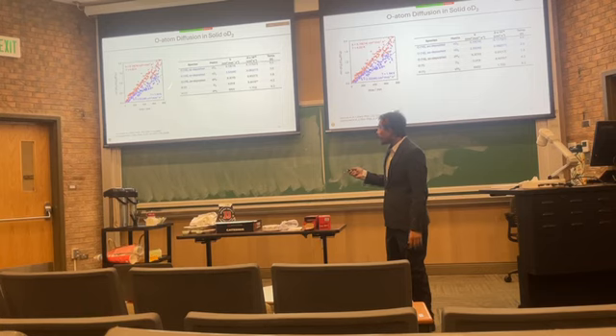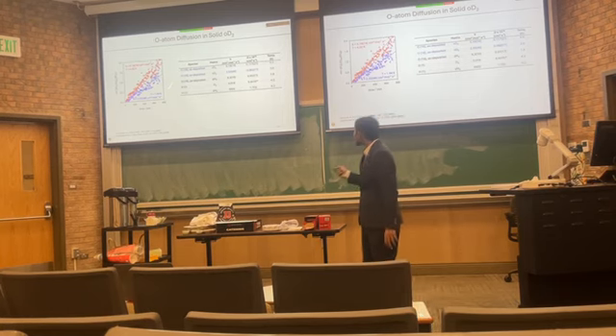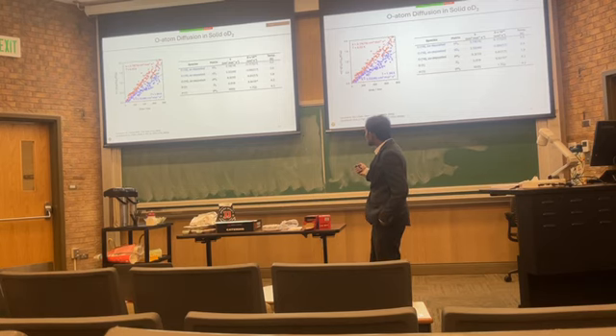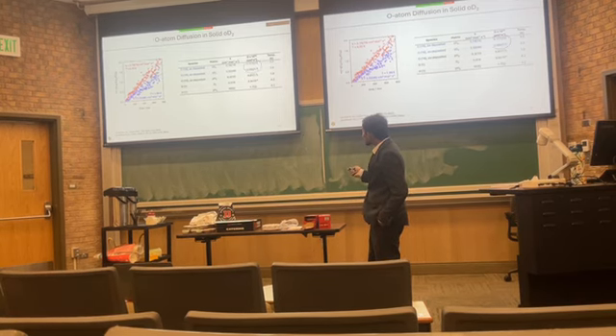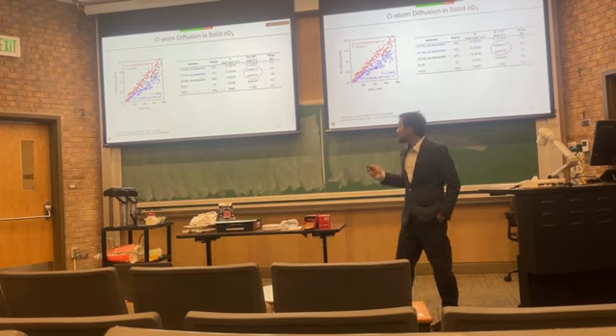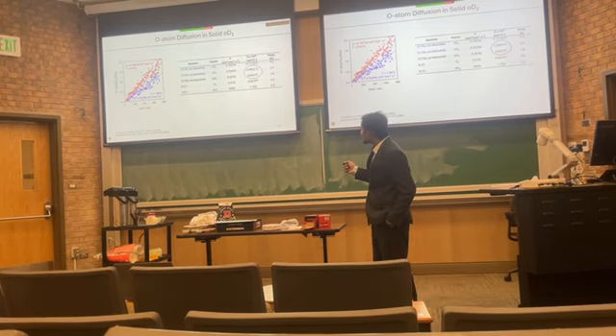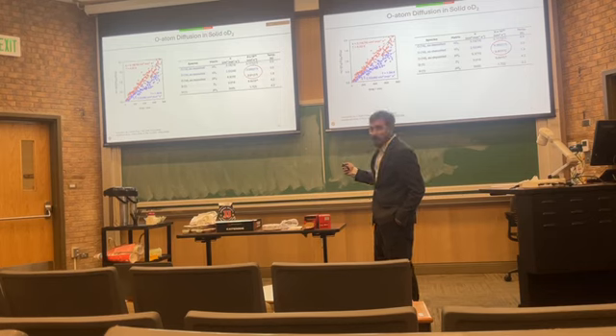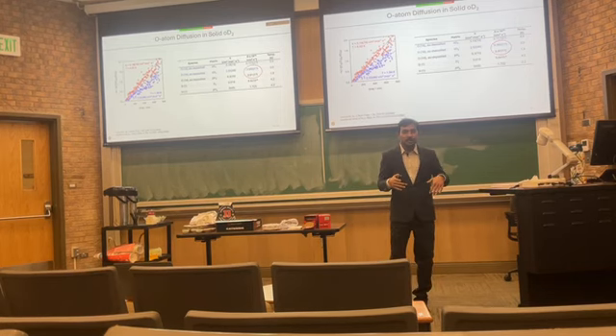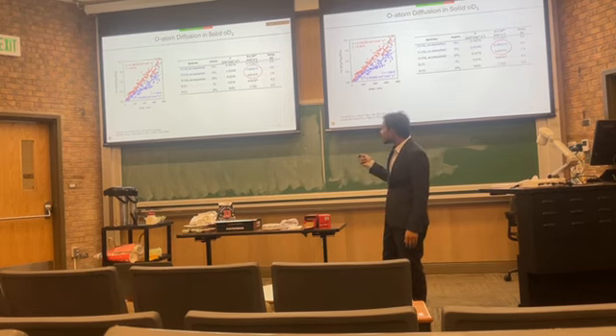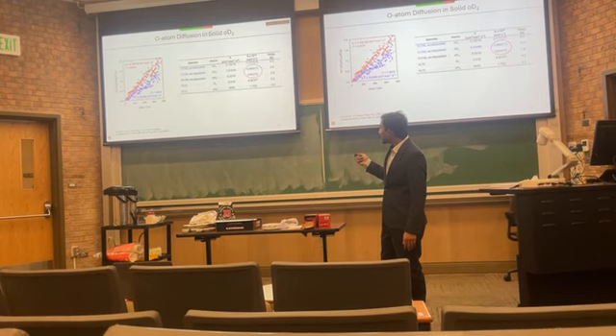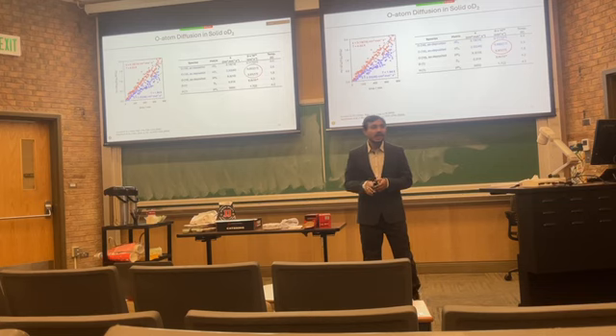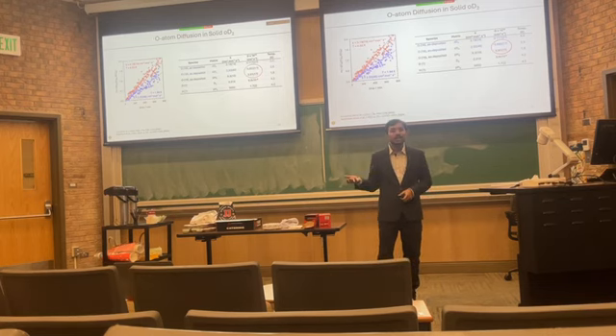So we compare our oxygen in orthodeuterium to parahydrogen. Let's compare 1.8 Kelvin and 2 Kelvin. Sorry, I had animation. If you compare these two, 0.09 and 0.81, it is one order of magnitude slower. In parahydrogen it was 0.81, in orthodeuterium it's 0.09. It's not that much slower, just one order of magnitude.